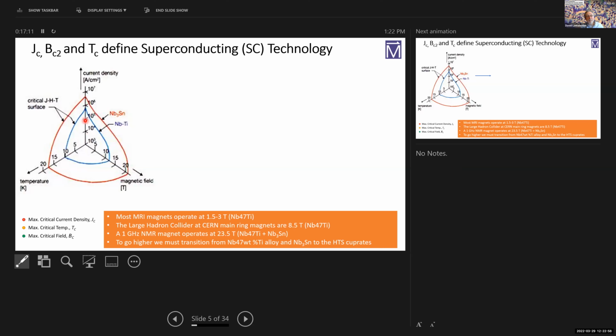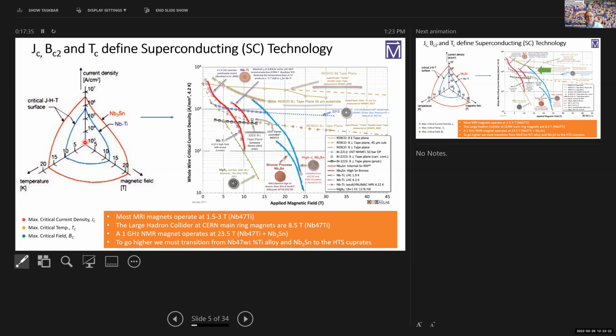So, if you think of currents as creating magnetic fields, so H equals nI in a long solenoid, then what you want, of course, is very, very high current densities. Typically you cannot operate copper at more than about 10 amps per square millimeter before it starts to get very hot in dense windings. Whereas superconductors, and this is a plot that's kept by my colleague here in Tallahassee, Peter Lee, essentially these are whole wire critical current densities for the various materials that you could purchase and therefore use practically.